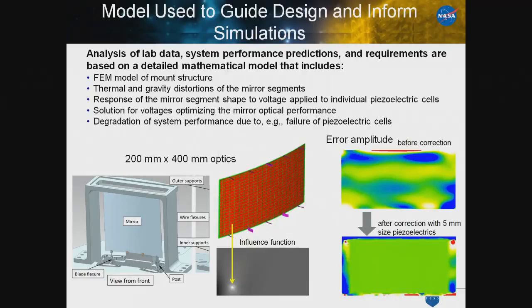We've tried to spend a fair amount of time thinking through many of the engineering details of this. How would you optimize the mirror optical performance? This shows a finite element calculation of the error amplitude of an optic from a previous generation telescope, where the color changes denote deformations of that thin optic. And this shows the surface figure that we predict that we can achieve using 5 millimeter on a side piezoelectric cells.